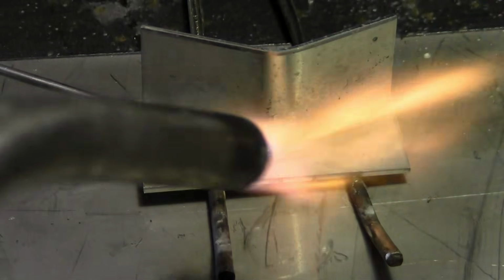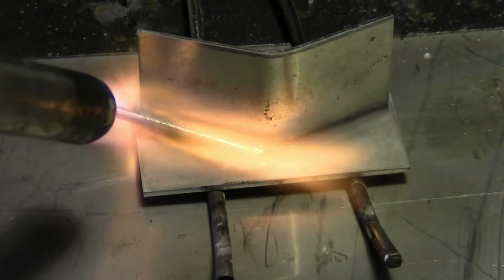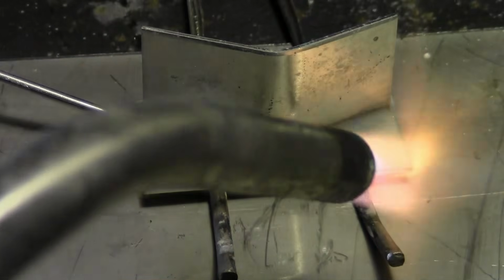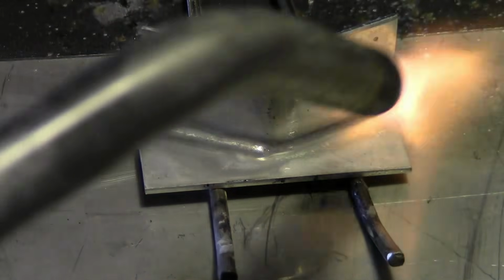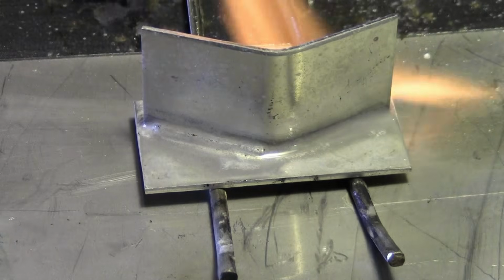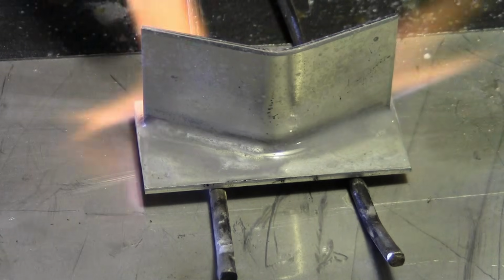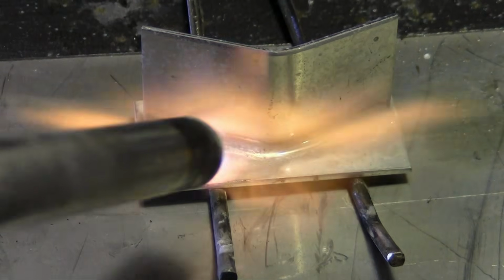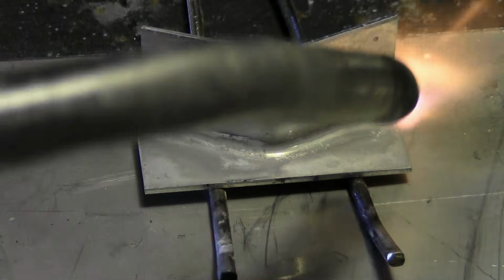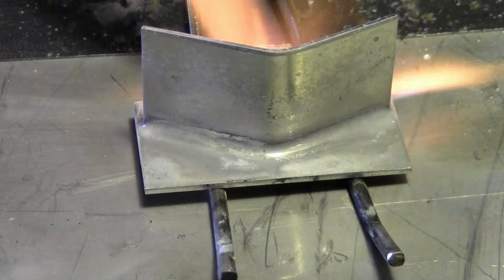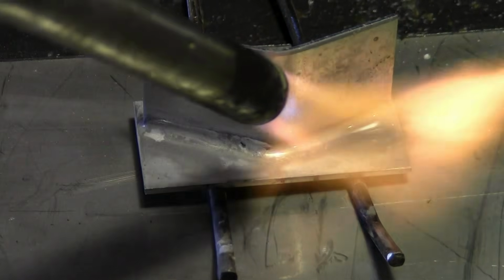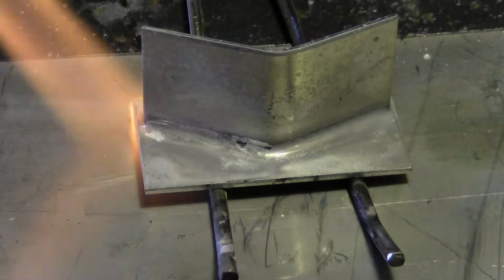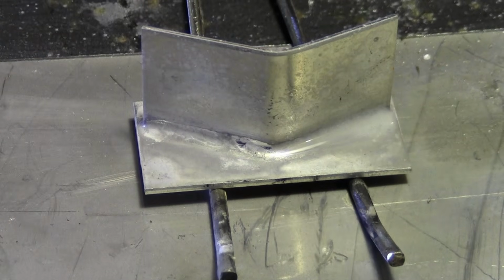The flux appears to be fluid and active. Let's deposit the Super Alloy 5 while heating the rod and the two plates where they meet, front and back, side to side. This technique should achieve an even fillet on the front and back of the piece. Let the aluminum cool naturally and remove the flux residue with warm water and a wire brush.